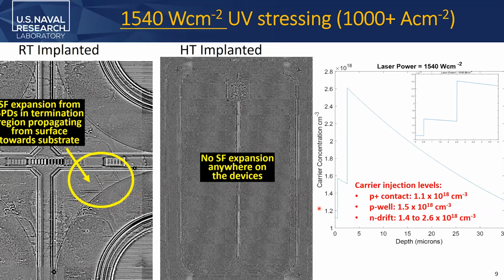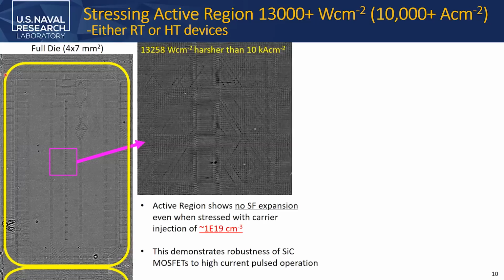So we wanted to look at it more carefully, and we take one of these devices and then we even go higher. This is the full die, and we go as high as 13,000 plus watts per centimeter, which is equivalent to 10,000 amps per centimeter square. And we have several defects that are generated from the termination region, but the good news is that the active region shows no stacking fault expansion, as I show you here. And the active region is the region that sees your high current injection, which demonstrates that the silicon carbide MOSFET, the 3.3 kV, is robust for pulsed operation, or it is immune to lightning strikes or any other things.